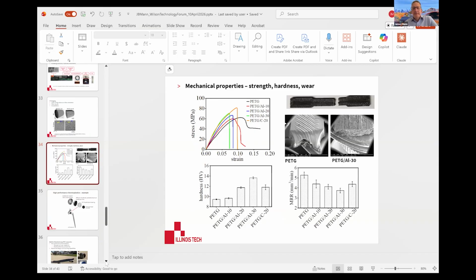And one of the things I want to point out to all of you is that in the tensile test response, this dark black line, that's the base. In this case, it's PET-G polymer, but it's the base PET-G. But look at all the other composite formats have much higher modulus, much higher ultimate strength, just a kind of remarkable result for the actual first published results in this space. It's really original work. There's really not too much for us to compare to out there in terms of metal fiber in this size scale.